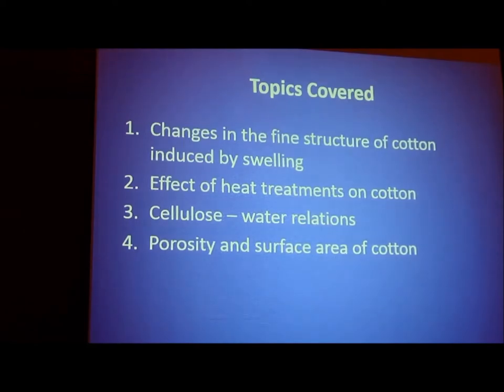Swelling treatments were known to change crystallinity, but it had not been determined how extensively and how substantially the modification would affect fiber properties. The terms accessibility and amorphousness were used synonymously at that time. The values for crystallinity ranged from 39 to 95%, depending on the technique used to determine it. Cotton has the cellulose 1 crystal form. Mercerization will convert it to the cellulose 2 crystal form, and amine or liquid ammonia treatments can yield cellulose 3. The conversion in these cases can be done with little or no degradation.